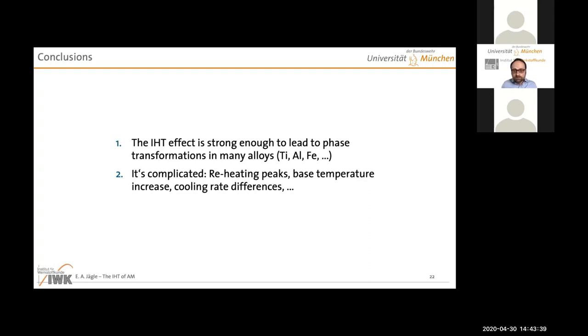But the way it is significant is rather complex. It can be the reheating peaks, it can be the base temperature coming from the bottom, it can be the base temperature coming from the electron beam from the top, it can be the cooling rates as in the last example. So this depends very strongly on the material and on the process, and not only on the process, also on the way you set up your process. Think back to the pauses. Also, things like the number of specimens on the substrate plate matters.